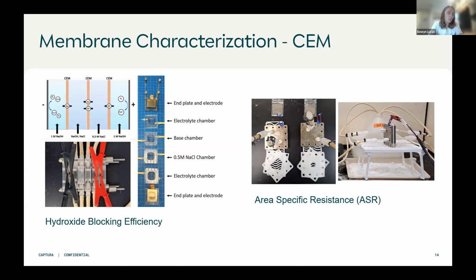Similarly, we don't actually currently make our own anion exchange membranes, but for any commercial anion exchange membranes that we work with, we do a similar process with acid on one side and salt on the other, and we measure the acid leakage across that anion exchange membrane. And then the other key aspect for a CEM or an AEM is just the resistance directly across the membrane. So we've put together these cells that are just simply electrodes with some gaskets and flow solution on either side, and do an EIS measurement to measure resistance across these membranes.